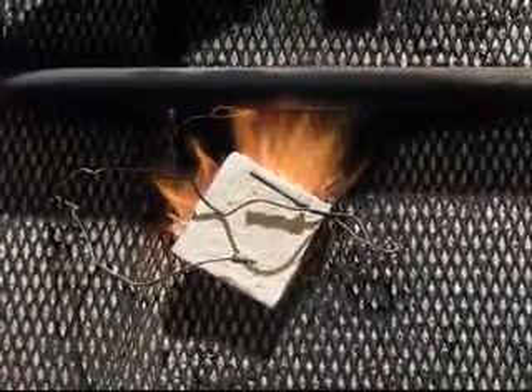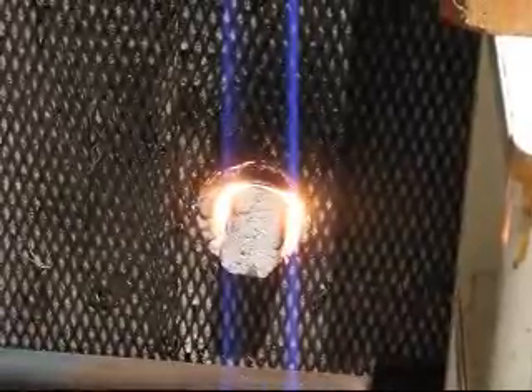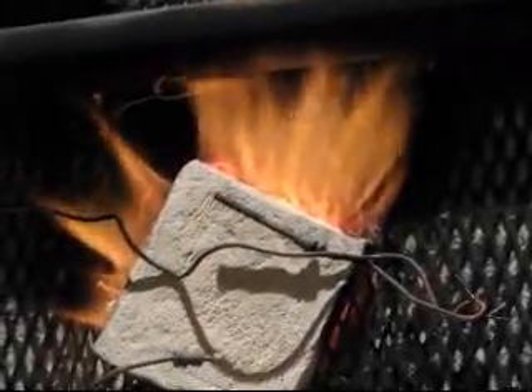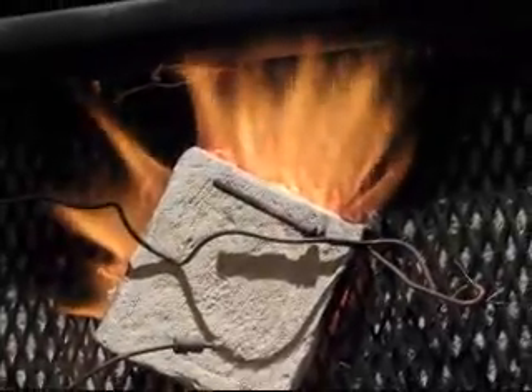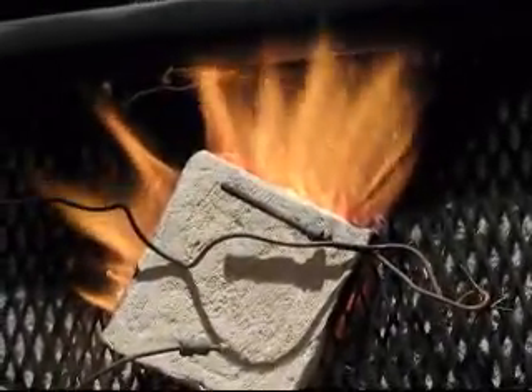Okay, the only thing I did was to plug up the holes in the damper, and I think you can see that the back pressure is significantly less in the top spy hole, and in the bottom spy hole it is also, there's much less back pressure, I believe. It's now 8:15 and cone 10 is down. That is the peephole at the top.